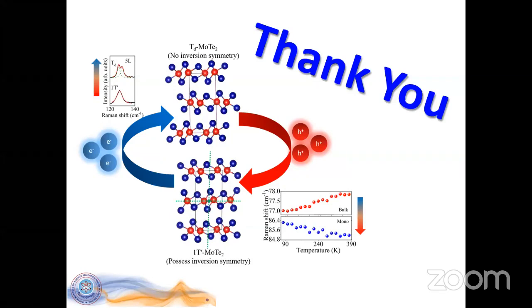MoTe2, the low temperature Td phase, shows a superconducting transition below about 100 millikelvin. Now that you can stabilize this in some way at very high temperature, did you also check what happens to the superconducting phase? With rhenium doping, clearly the critical temperature goes up, but when you thin down MoTe2 without any rhenium doping, what happens to the superconducting phase?